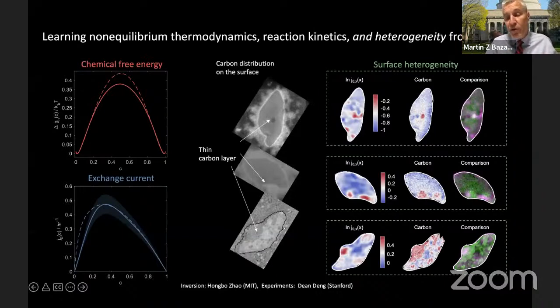So amazingly, for all of these particles, just by having these images, and it's only 6 or 7 images per particle, we learn the model and we non-destructively image the surface. And I don't think this has ever been done before for a heterogeneous catalytic surface, because there are many problems in chemical engineering, electrochemistry, where the net reaction rate that you're interested in is actually driven by microscopic heterogeneities.